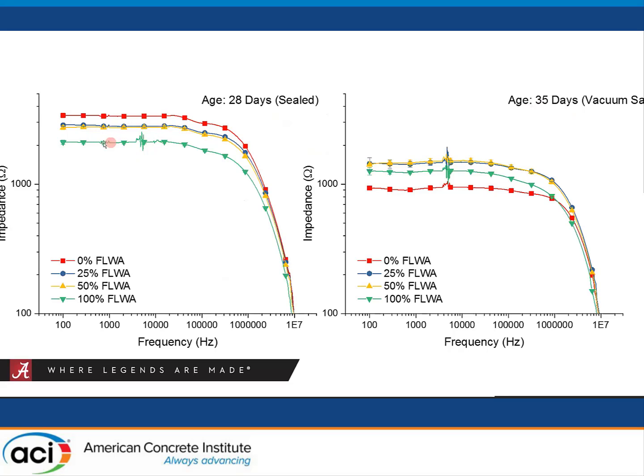It's not necessarily the issue of the impedance value. We expect it to go down a little bit because we're going to saturate it in a representative pore solution that's calculated using the NIST pore solution calculator. But what's more striking is the order in which the values change. So at the sealed state at 28 days, we have the highest impedance at the non-internally cured mixture, then the lowest with the internally cured. But then that switches after we dry it and then resaturate it.